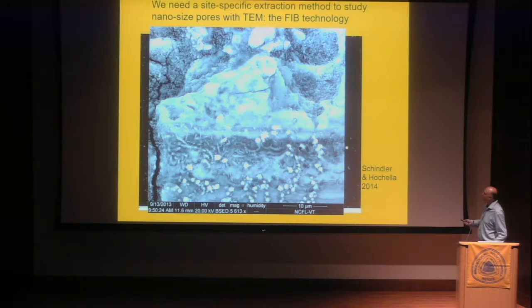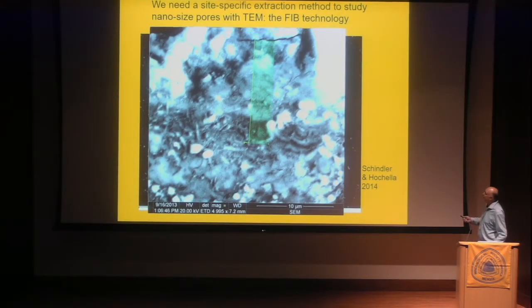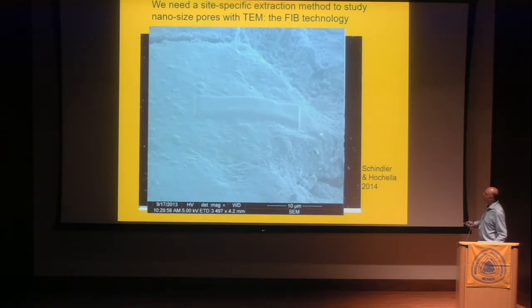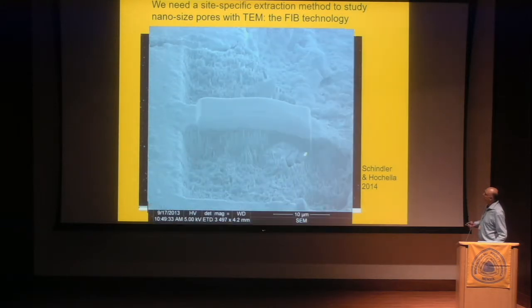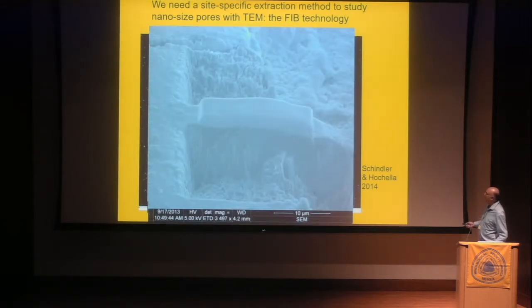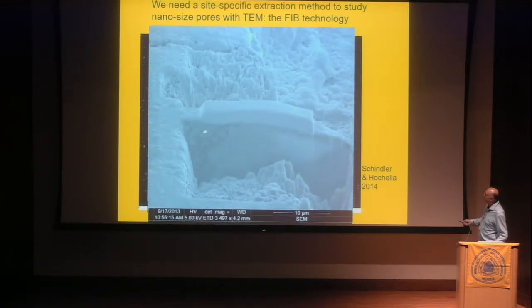So when you have here a mineral surface coating, you do first scanning electron microscopy and you pick an area of interest, and then you zoom in and you see here, for example, this interface, and you want to look now at this interface and the mineralogy of the confinements along this interface. So you mark your area that you want to look at, then you put a protective platinum glue on top, a little bit thicker, and then you sputter with gallium ions from both sides to create a trench, and you keep the protective area intact.